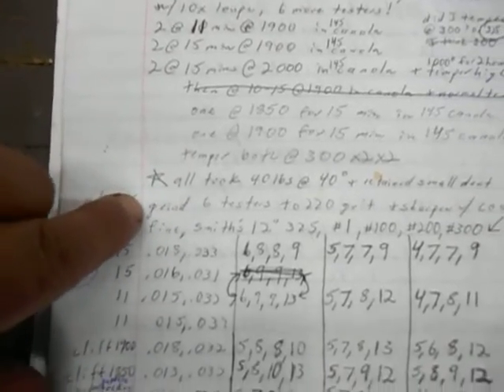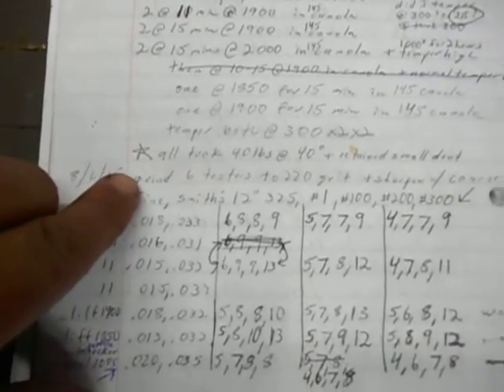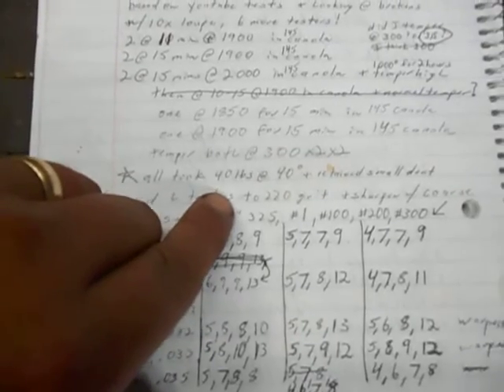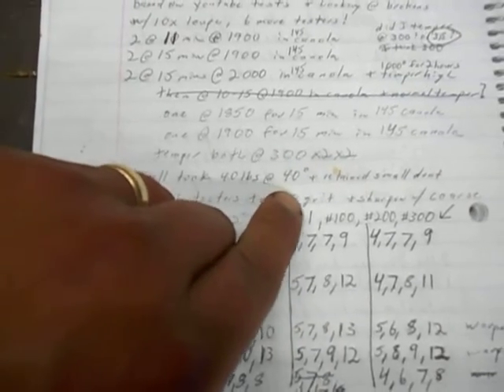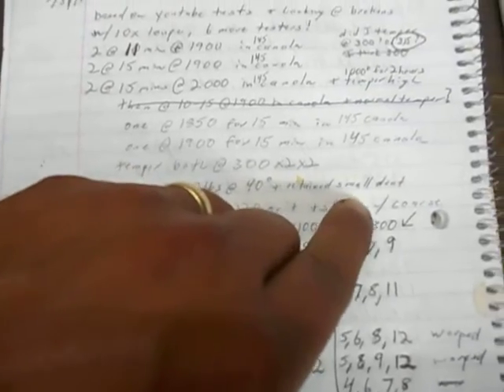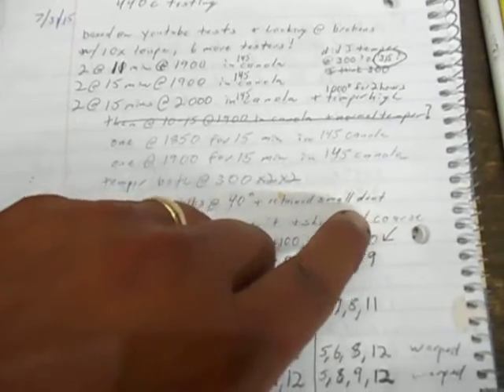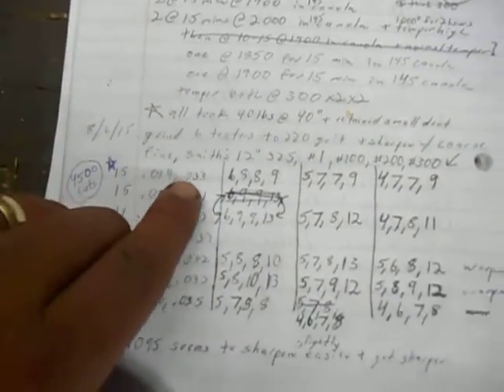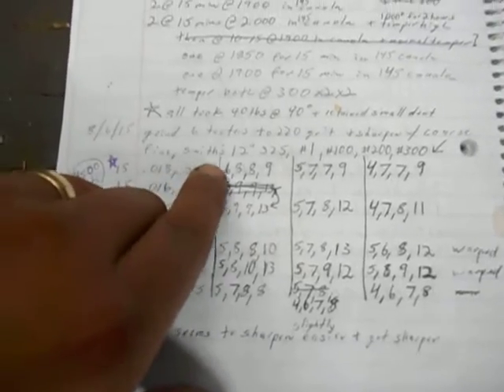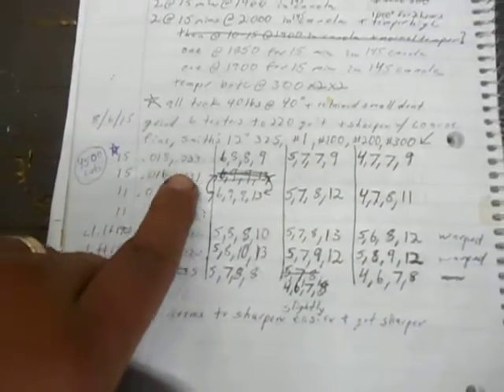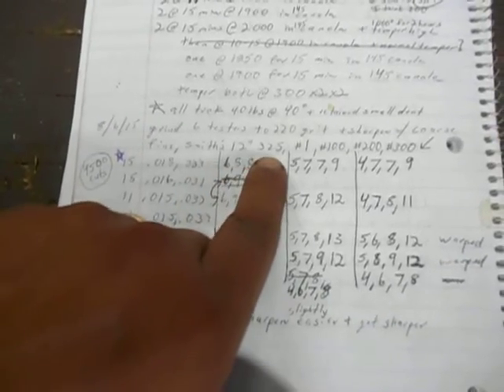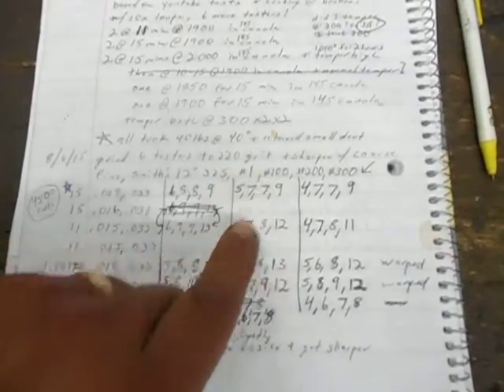Once they got out of heat treat, all six of them took 40 pounds at roughly a 40 degree angle and retained very small sets in the edge over the brass rod. Ground all six testers to 220 grit and sharpened with a coarse Smith's 12-inch 325 grit diamond hone. Now these cutting tests, move to the other side here.